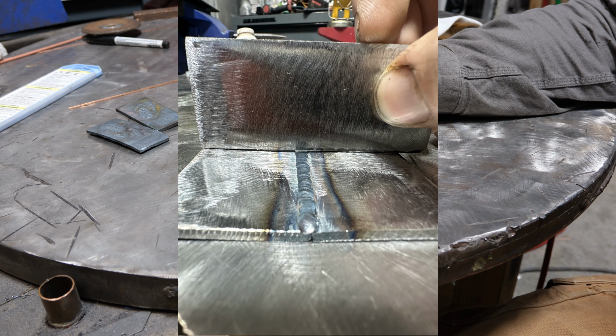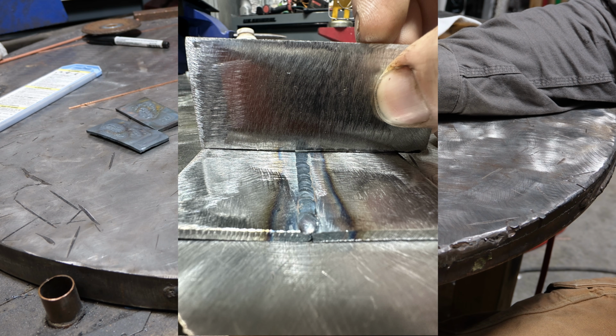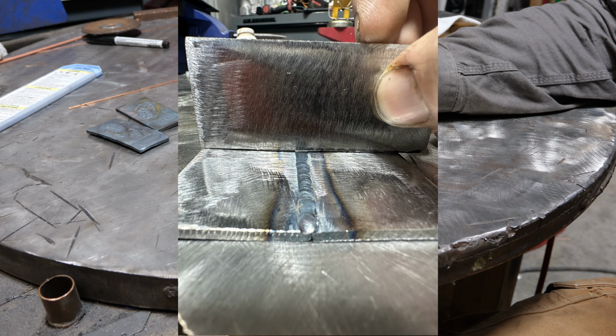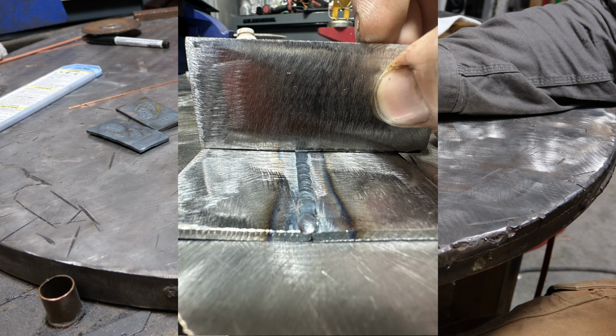One of the things that happens when you do fusion welds with no filler is plates tend to warp a bit. In that picture, you can see that the plates are more or less a V. That becomes exaggerated when you don't add filler. When you add filler, oftentimes it'll be a little bit flatter. The second thing that you can see is more or less this whole weld is underfilled. It is below the surface of the plates. Now that is to be expected because we didn't add additional filler metal for reinforcement.